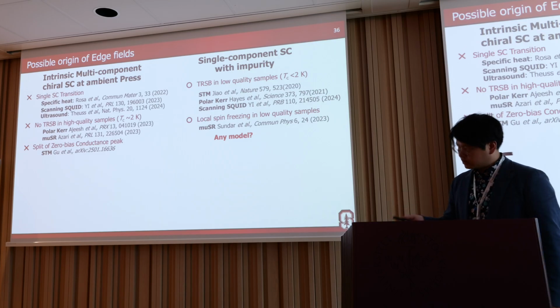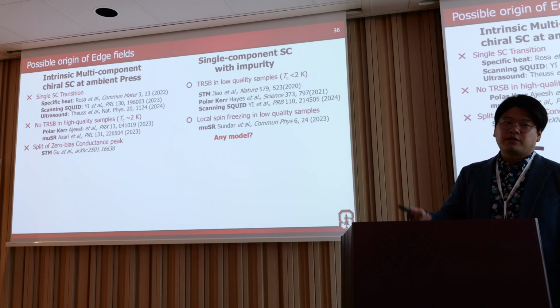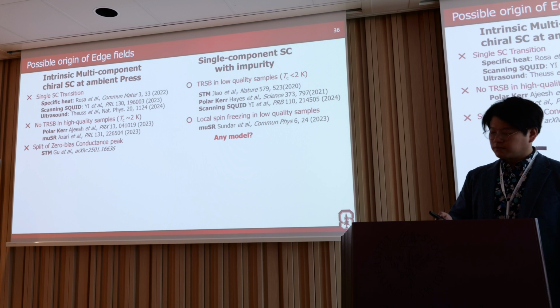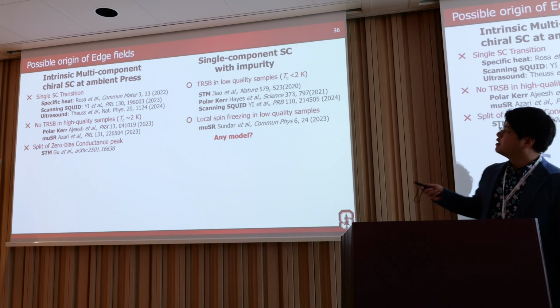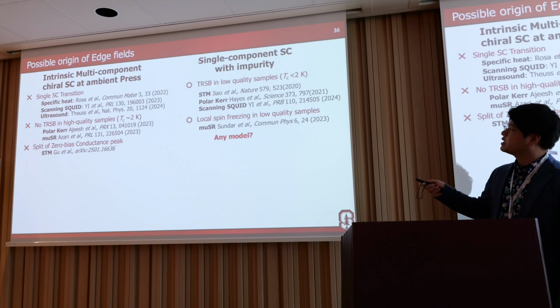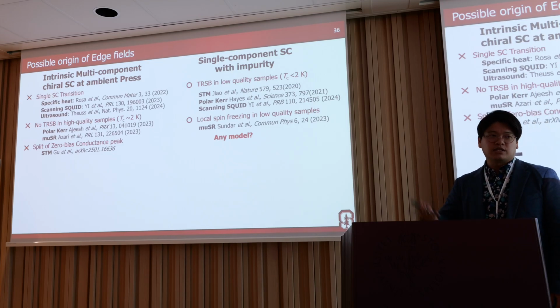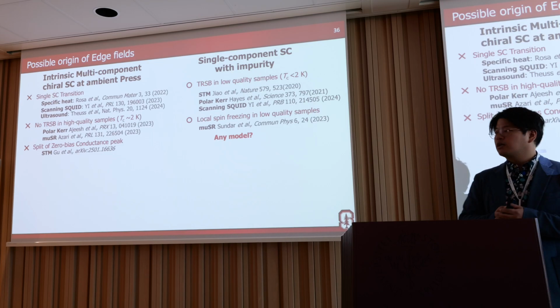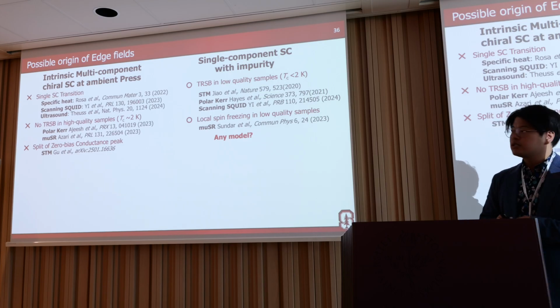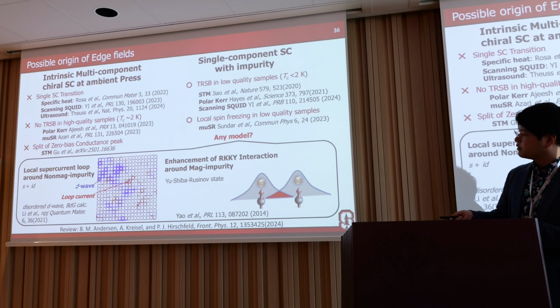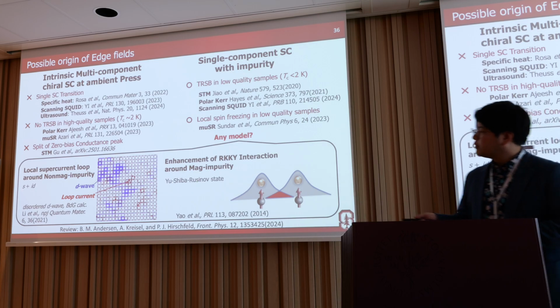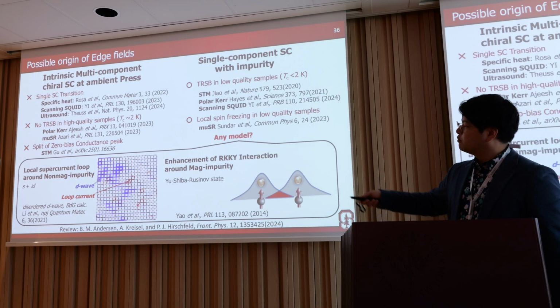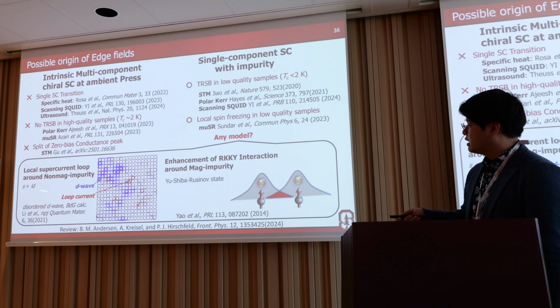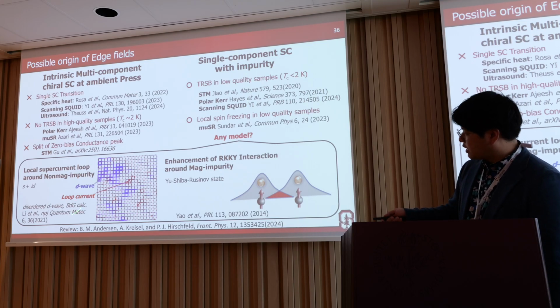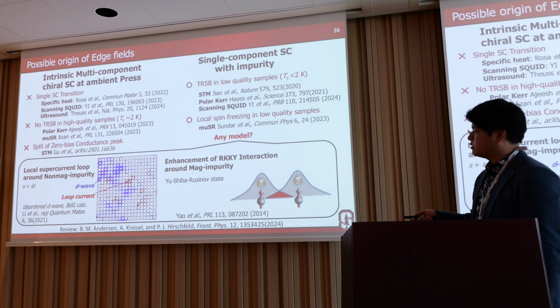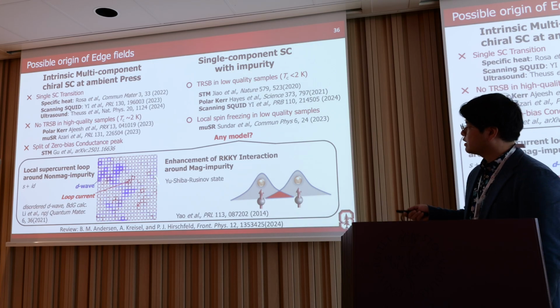So then we need to think about an impurity model, an extrinsic model, because an impurity model may explain why we only see this time-reversal symmetry breaking in the lower TC sample. But what existing models may explain this? There are two examples I got from a review paper. One is a local supercurrent loop around a non-magnetic impurity, like s plus id, but they only calculated it for the d-wave case. So we cannot simply apply this one to our case.